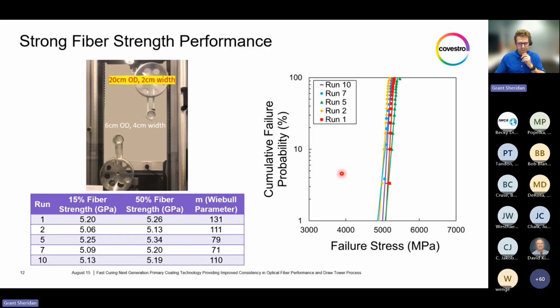And shown here are the cumulative failure probability of five fibers of the next generation coating, encapsulating the extremes of the conditions run, including draw speeds from 1300 to 2800 meters per minute and glass temperatures from 42 to 120 degrees C. Despite the extreme range in draw speed and glass temperature, all 5 fibers demonstrated excellent fiber strength over 5.1 gigapascals, with M values close to or over 100, which indicated excellent data point consistency.